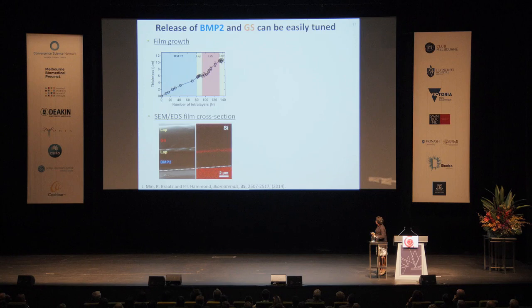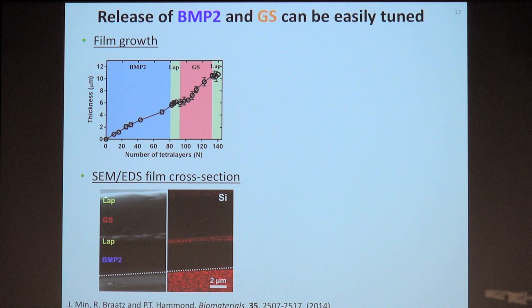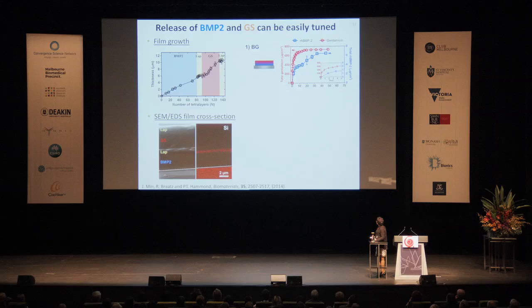You can also use electron microscopy to see the structure of her film. Here, the brightness shows where the silicate is, and she used a silica kind of underlayer, BMP2, the laponite clay layers, gentamicin sulfate and laponite. And in red, you can see that she was using essentially a version of this electron microscopy in which you can see the atomic nature by looking at colors. So here, red indicates silicon atoms. And you can see that we have this separation between the layers with the film. So she has these very nice separated systems, and she can vary the release characteristics.